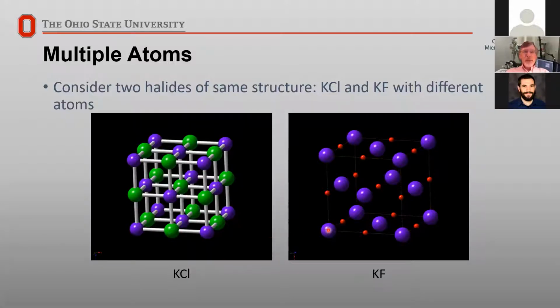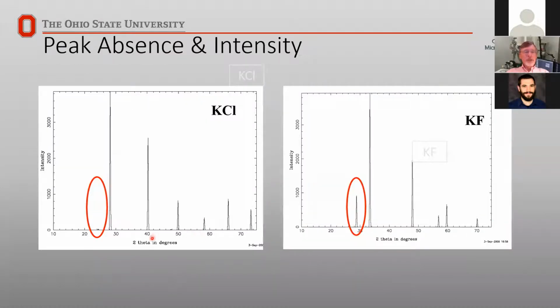Now, the potassium fluoride, and it's a little harder to see, has the same cubic crystal structure as the potassium chloride. The difference is now that we have fluorine atoms, which are much, much smaller. Potassium and chlorine are very close to each other in the periodic table and will scatter at about the same amount. The potassium and fluorine scatter much differently, so you get a different amount of scattering from the two atoms. So if we look at the patterns that come from these two structures, we get something like this.